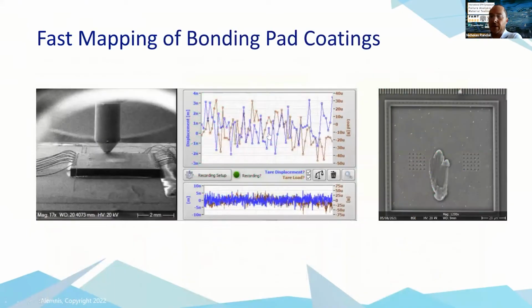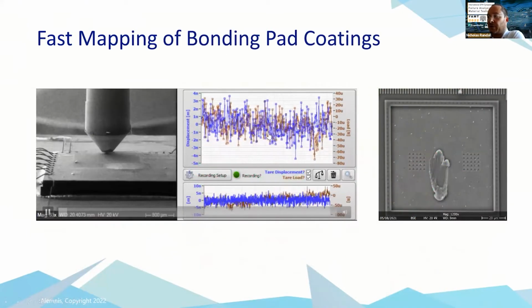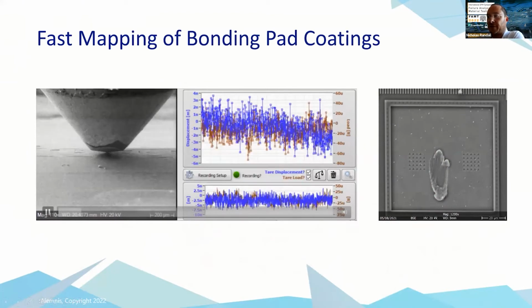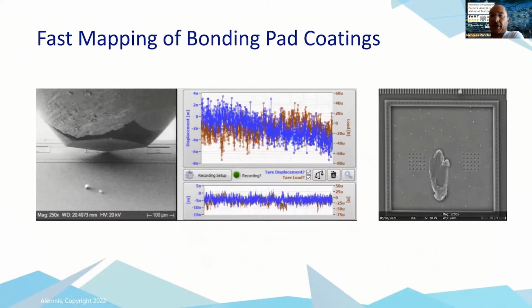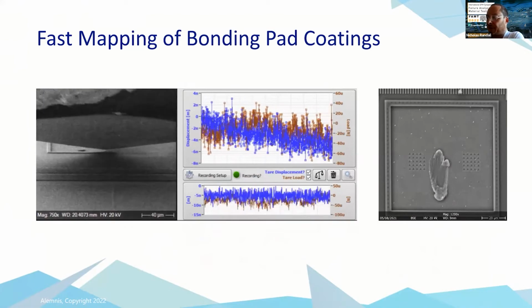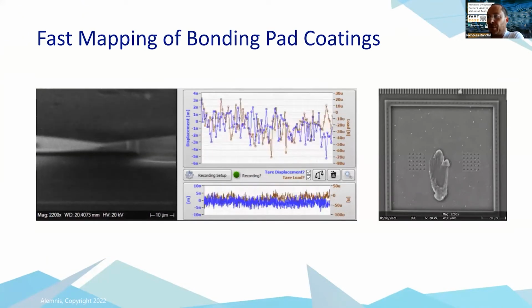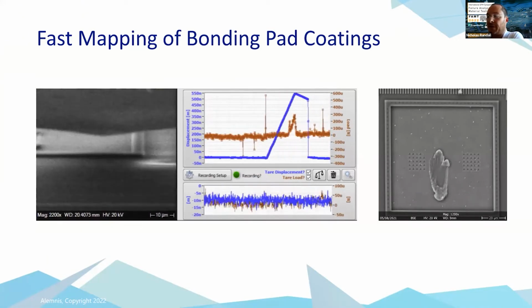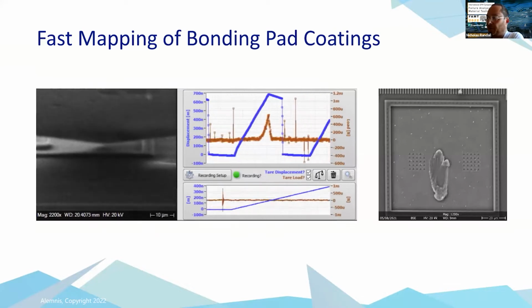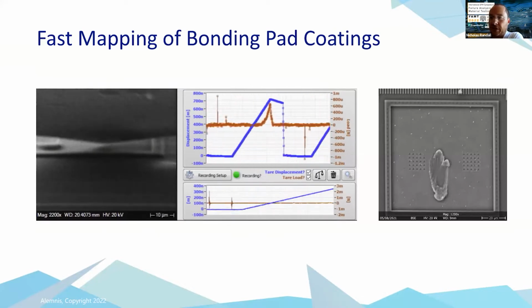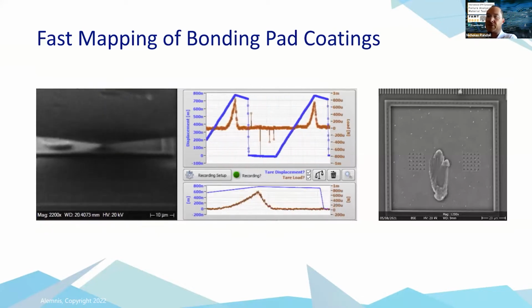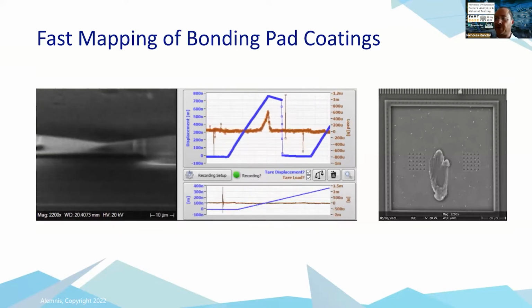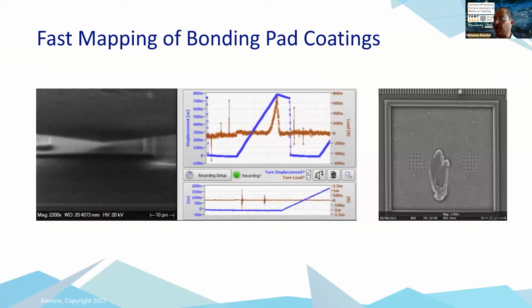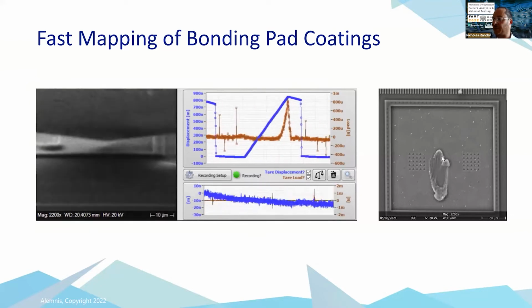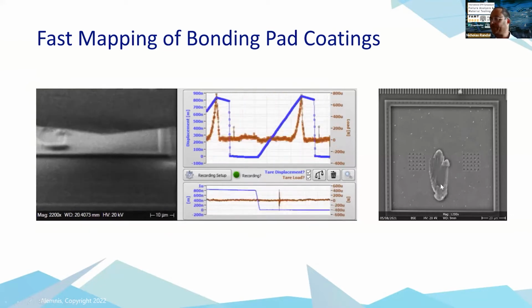So in the case of semiconductor, we're often interested in making fast maps to check coating properties. This is a bonding pad coating, and we're doing small, fast arrays of maps in different areas on the bonding pad to understand the integrity of the aluminium coating, which is deposited on the pad. And of course, we've got to be very localized because we don't want to test where there's a scrub mark.